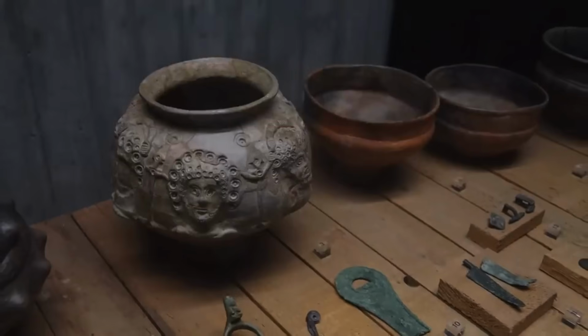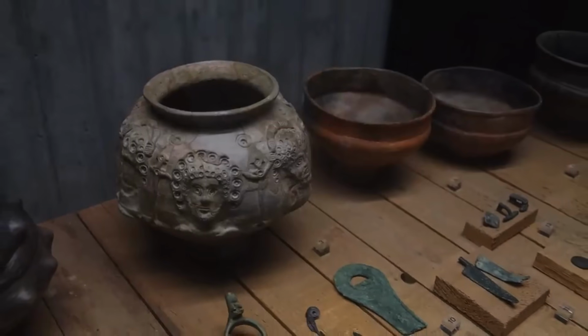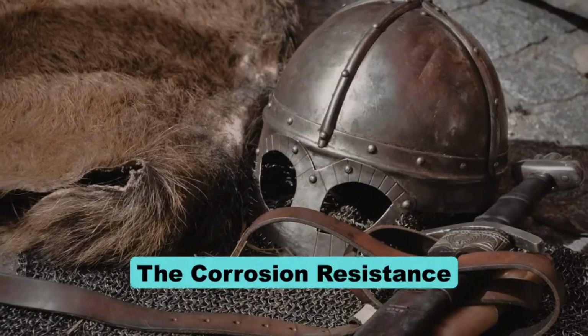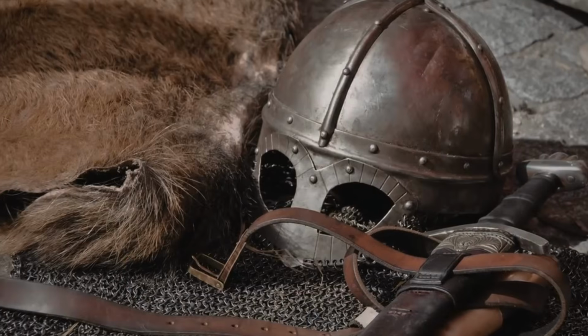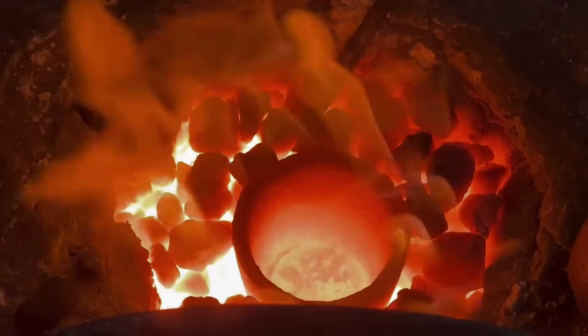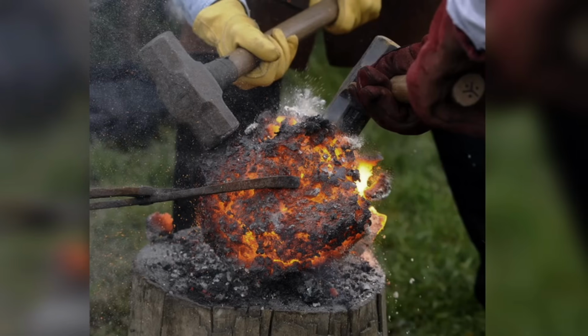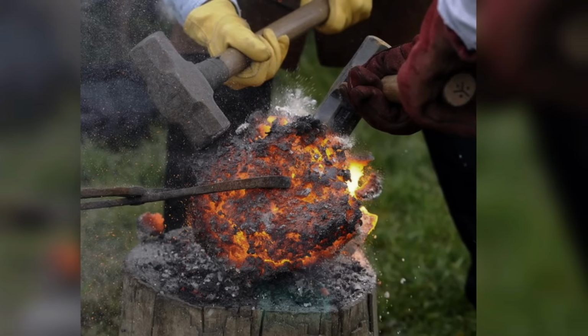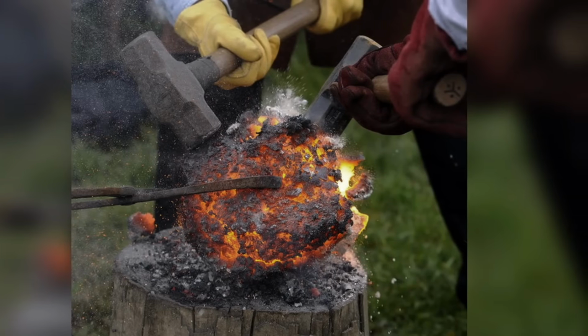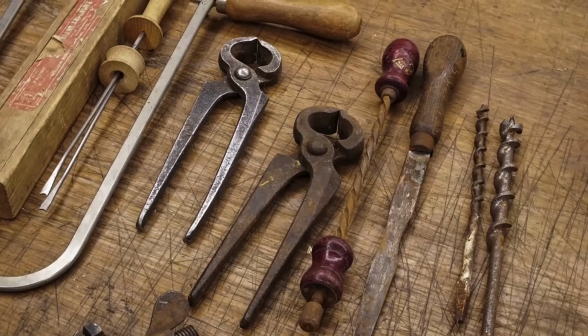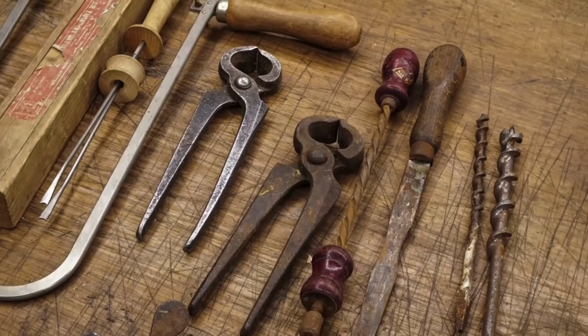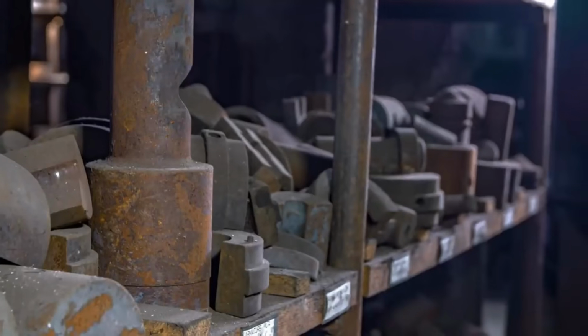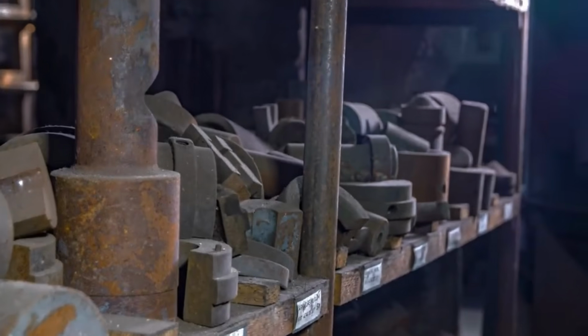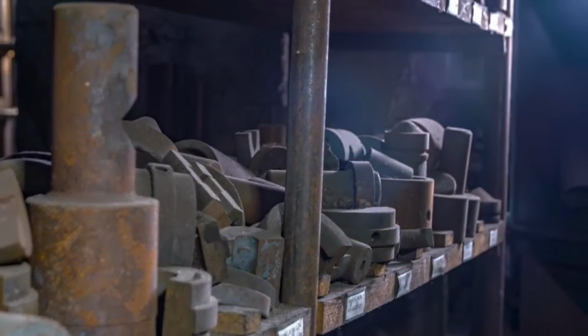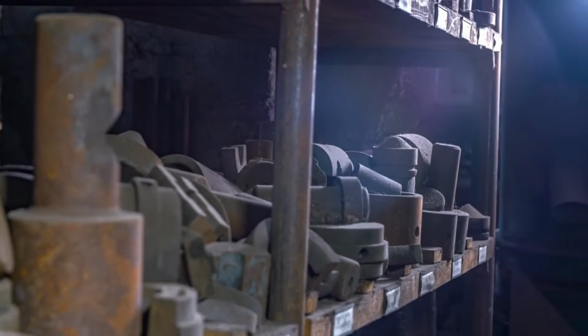This is where medieval iron picks up the third critical feature, the one that explains the corrosion resistance. The slag never fully leaves. Even in a fully worked bloom, between 1 and 3% of the final iron mass is still slag, distributed as thin elongated stringers throughout the metal. Modern metallurgists used to consider these inclusions a defect. We now understand they are part of why the iron survives.